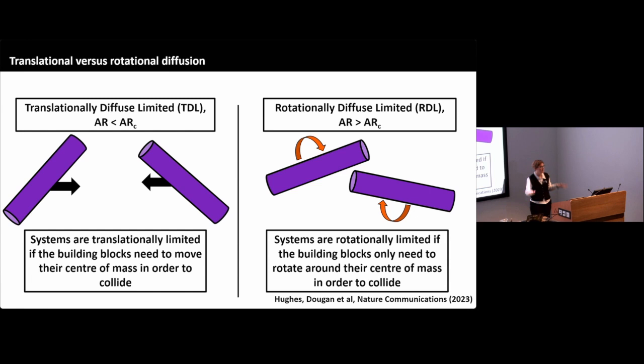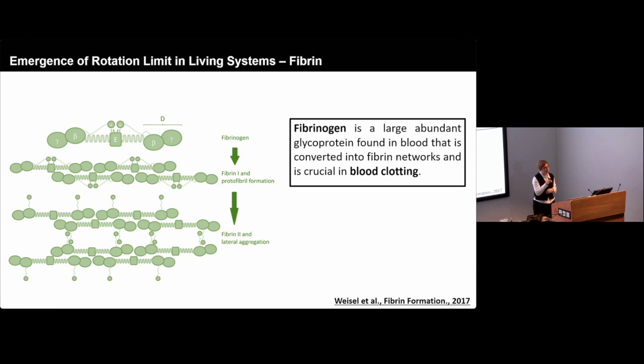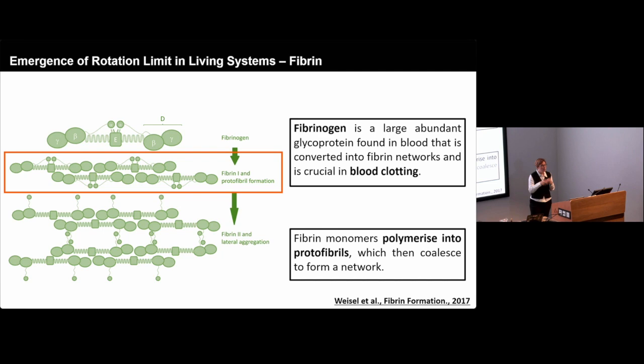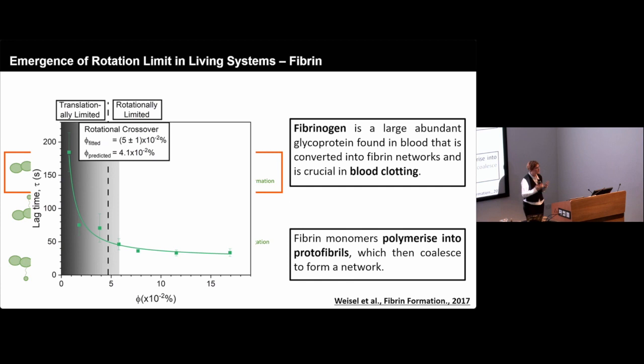And so what's really interesting is when we did the same thing for a biological system, in this case, fibrin. So fibrinogen is this large, abundant glycoprotein, which is important in blood clotting. And these fibrin networks are really crucial. And so the fibrin monomers polymerize into protofibrils, and that's what forms the network. So if we take some fibrin, we form a network, we measure the lag time, and we look at that as a function of concentration, we see this similar crossover from being translationally limited to rotationally limited in the way